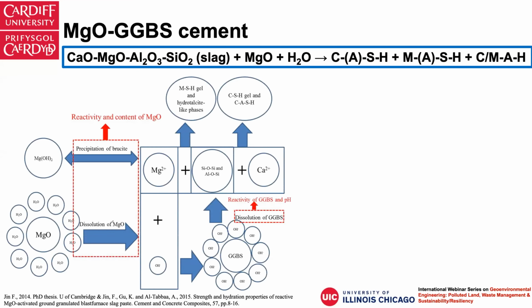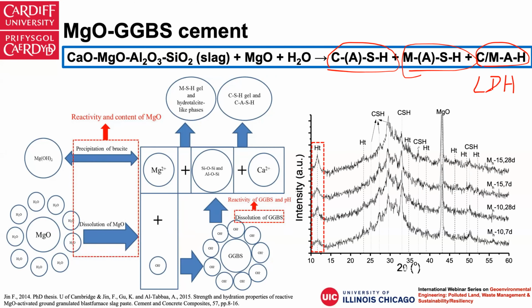But if you mix it with magnesia, the hydration of magnesia creates an alkaline environment that will attack the slag particles to release all of these monomers and polymers, and then they will rearrange and precipitate or crystallize into various kinds of reaction products. These include common cementitious products like CSH, calcium silicate hydrate, magnesium silicate hydrate, as well as the last one, calcium aluminate hydrate or magnesium aluminate hydrate. This is commonly called layered double hydroxide, we call it LDH. So this is a very interesting phase I found in this type of cement, and it has lots of implications for soil remediation. From the X-ray diffraction, we can see a very clear peak of this phase.